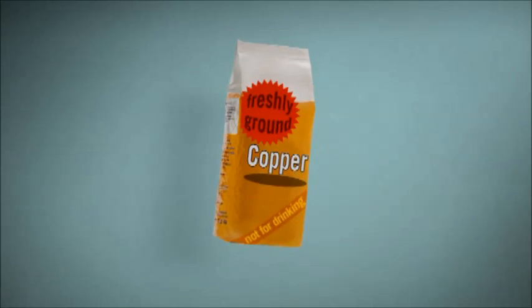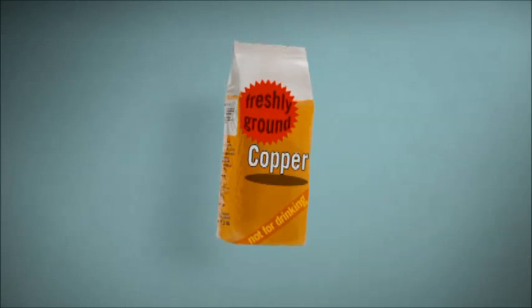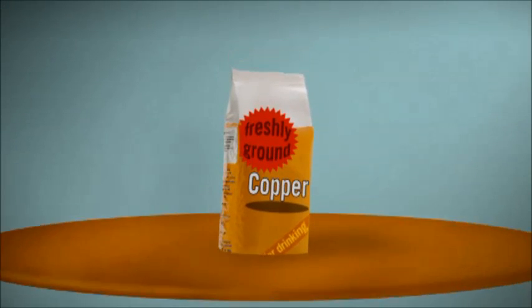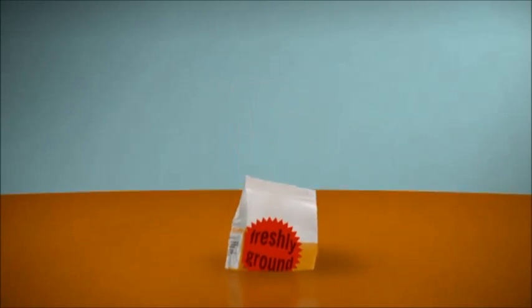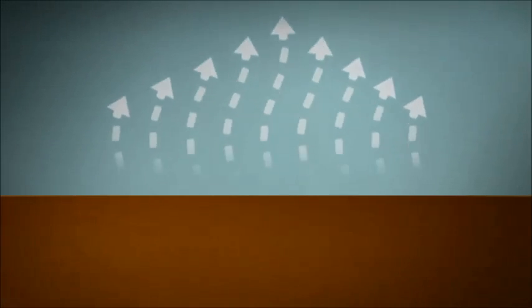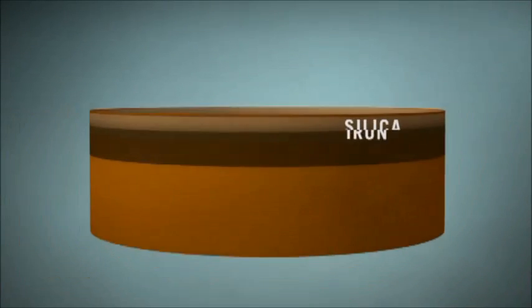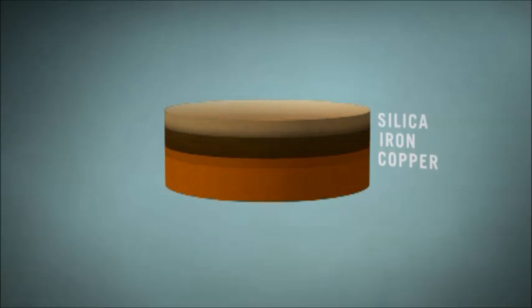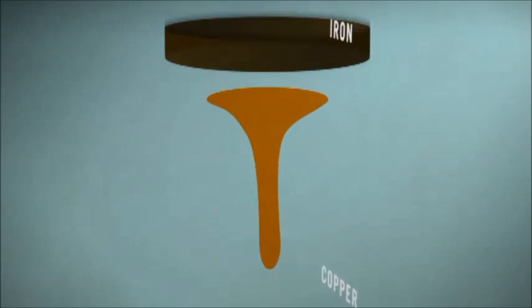This powder goes into a large, very hot flash furnace, which causes the dried concentrate to melt and turn into a molten metal called matte copper. During this process, sulfur gases burn off and are then captured and cleaned. A combination of iron and silica rises to the top, and the heavier copper matte sinks to the bottom. This matte, which is now about 70% pure copper, is collected.